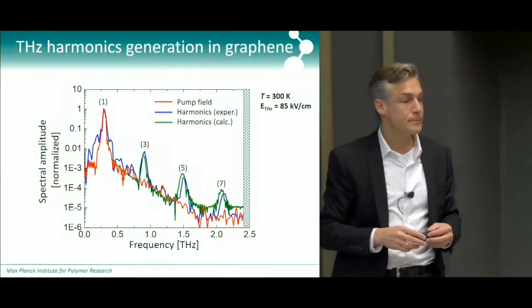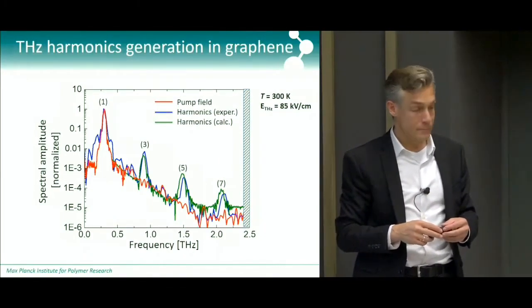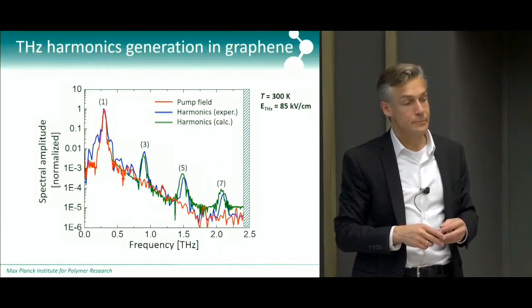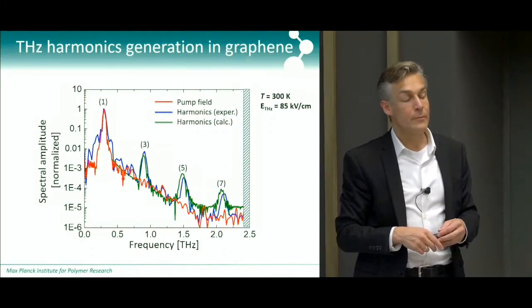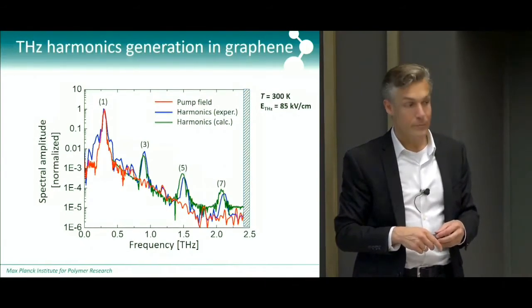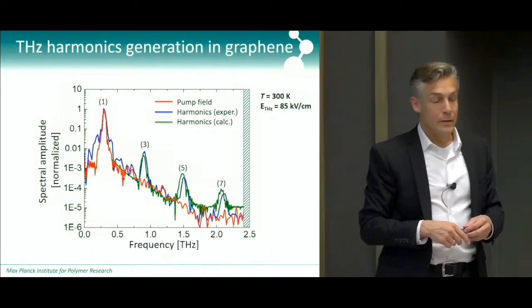I understand the hot electron picture and the thermodynamic machine, but this mechanism would also be true for any metal that you would heat with some electric field. Any metal you would drive with an electric field would heat up, and so the thing that really makes your story special is about those harmonics and these coefficients that are presumably higher for graphene than for other materials. Why is it that graphene has this?